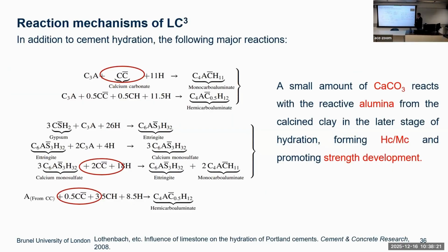Okay, and the reaction mechanism of LC3 shows that a small amount of calcium carbonate can react with the aluminate phase from calcined clay. Remember we have the silicate phase and the aluminate phase. The silicate phase reacts earlier, hydrating earlier, but calcined clay has a much higher aluminate phase than Portland cement. So that's why we ask whether we can use carbonation technology to generate hemicarbonate aluminate and monocarbonate aluminate, which could have a positive effect on strength development.